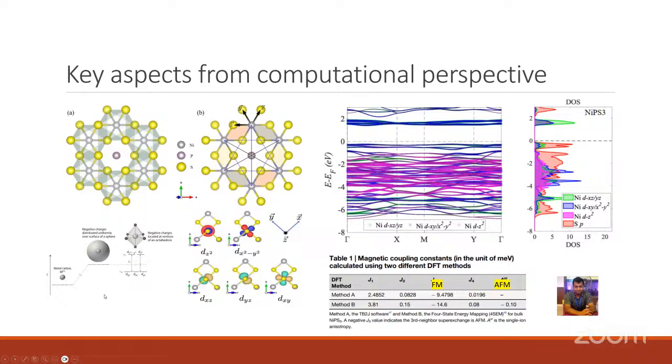And also for this system, the transition metal ions are sitting in the middle of an octahedral crystal structure. The octahedral structure will split the 5 degenerate d orbitals into 2 higher Eg orbitals and 3 lower T2g orbitals. As I mentioned earlier, each transition metal ion carries a different spin momentum.